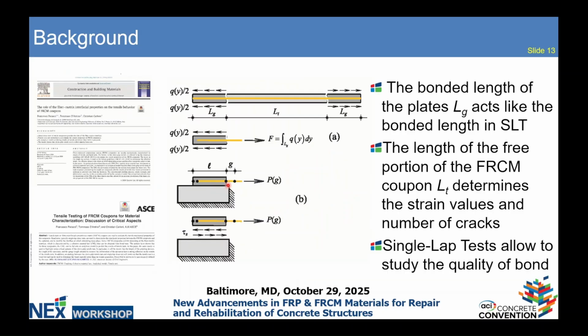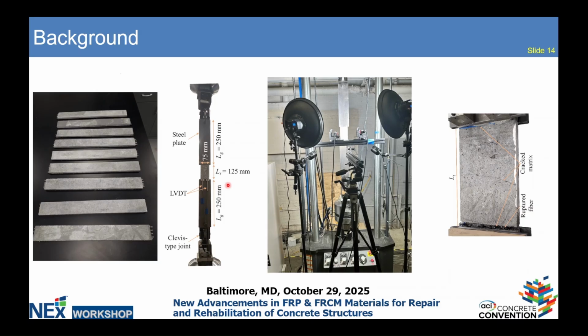We have proven, and I don't have time here, we have proven that if you do correctly the clevis type test, you actually get exactly the result of a single lap test, properly done. The issue is, again, it's fairly long, and also if you do a clevis and not a single lap, you will never know if your composite bonds well to this substrate. You only know what happens to the composite. And there are cases where the composite doesn't bond well. It might be it needs more surface preparation, and so forth. So these are some picture of some tests. We have done a lot of them.